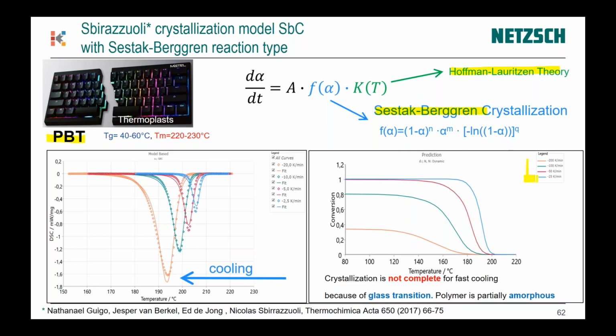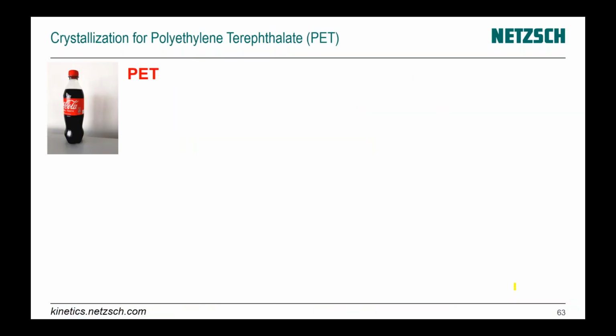Let's see: for slow cooling simulation, crystallization is complete - this is cooling from high temperature to low temperature. For fast cooling, crystallization is not complete. Why? Because we go very fast to low temperature and there is not enough time for the material to crystallize. Then we reach glass transition and everything stops - nothing happens. Here is PET.